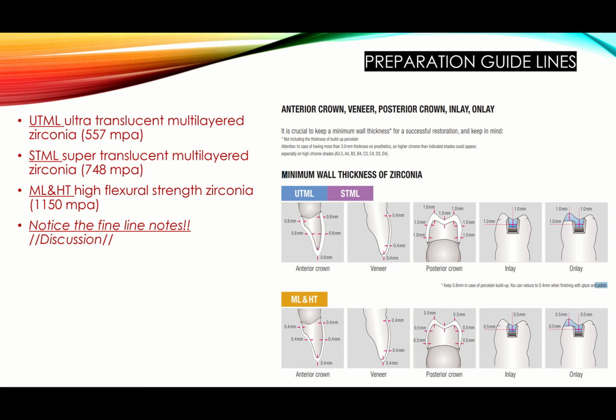I think it's too thin, and even in the manufacturing process, I do not like to mill anything less than 0.6, 0.7 millimeters on my CAD/CAM, even though it's a 5-axis CAD/CAM and it's stable and there isn't much vibration in the machine. But whatever, I just find that 0.4 or 0.5 millimeter shell is really susceptible to cracks and micro cracks, and it can fracture.